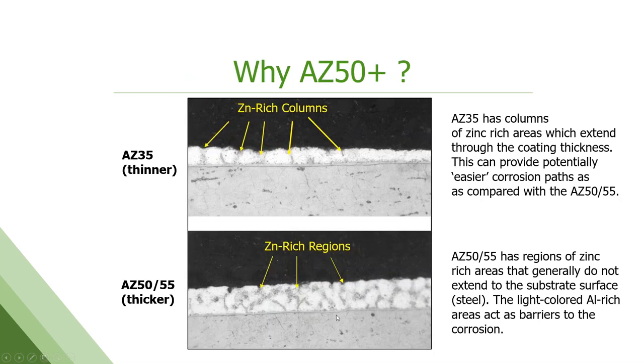So going back to the coating weights, here's a little explanation as to why this thinner coating weight can be problematic in exterior applications. This is a scanning electron microscope, so we're looking at the microscopic level. In this case, the white is the aluminum. All this white fluffy stuff is the aluminum. The dark gray is the zinc tunnels or zinc dendrites. You can see on the lower coating weight at the top here that some of those zinc tunnels come all the way down to the steel surface. So once those get corroded away, you're going to have a direct path to the base steel. Whereas in the higher coating weights, those dendrites don't usually come all the way down, and you have a lot more aluminum there to continue protecting the surface. So that's why the higher coating weights are warranted and are better for exterior use.